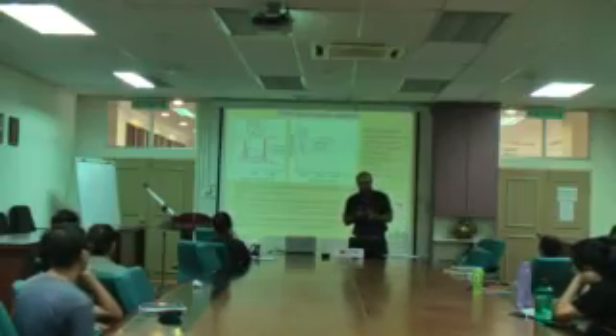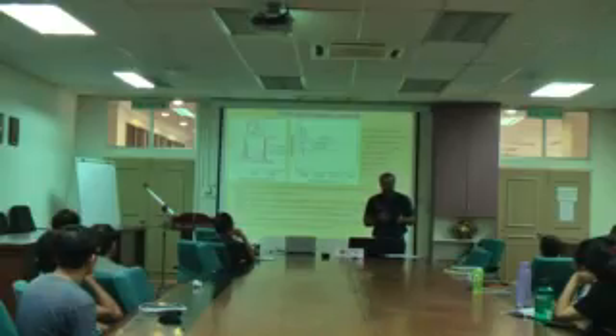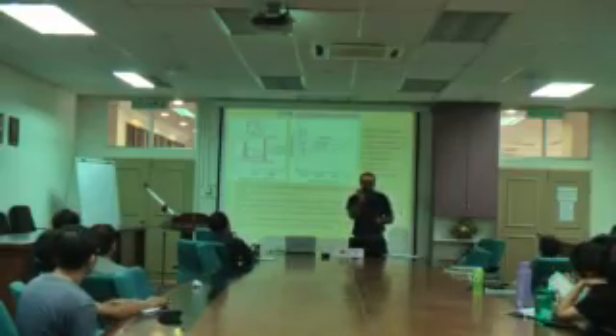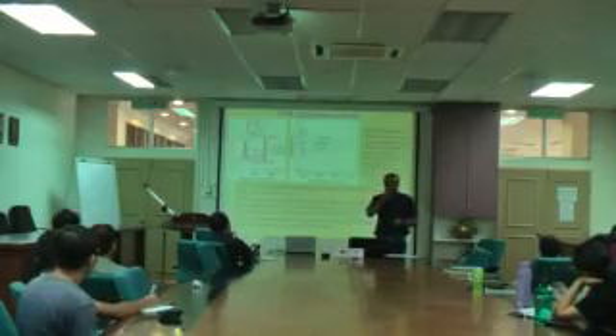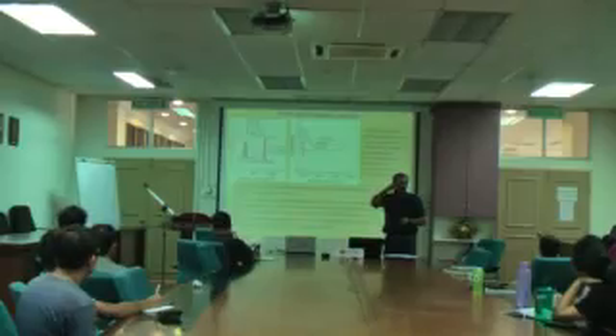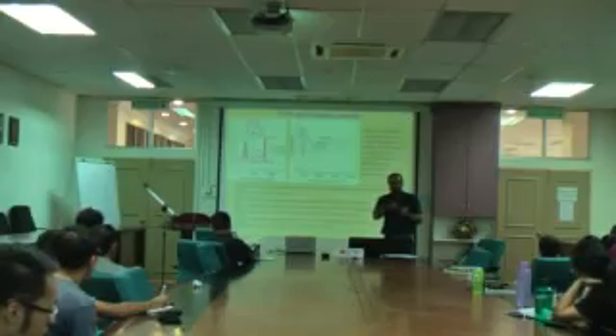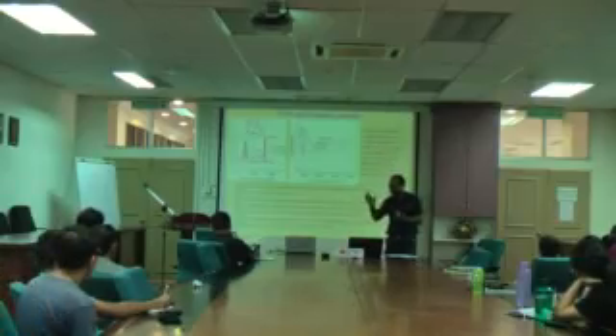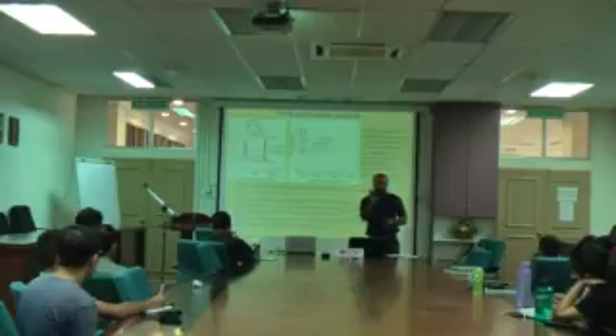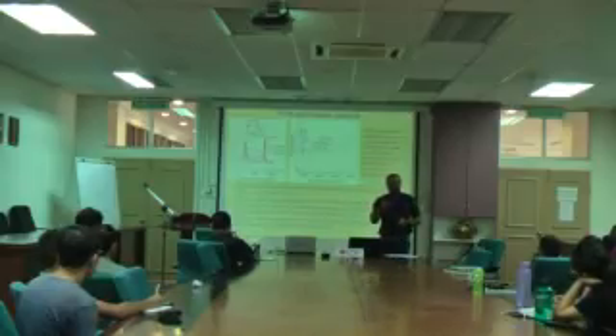So we have three kinds of confinement, yeah? Strong confinement, weak confinement, and intermediate confinement. So if we want to see the strong confinement effect, we should prepare the size below the exciton Bohr radius. What is exciton Bohr? Exciton Bohr is not the radius of the molecule. Exciton Bohr is the distance between the excited electron and the ground state, I mean, the ground state and excited state. So if you want to see the strong confinement effect, you should prepare the particle within this exciton Bohr radius area. Exciton Bohr radius for germanium is 24.